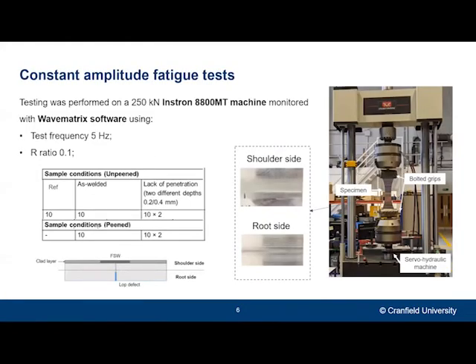So in order to study this, I performed some fatigue tests using an R ratio of 0.1 and a test frequency of 5 Hz. And as you can see in this test matrix, I tested 5 different sample conditions. So I have samples without any weld, so that's just the pristine aluminium material, which I'm calling reference. Then samples in what we call welded condition, so samples presumably without any defects. And finally, samples with 2 different defect depths, 200 and 400 micrometer.